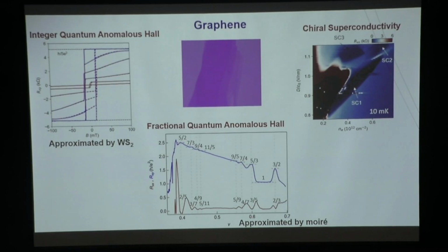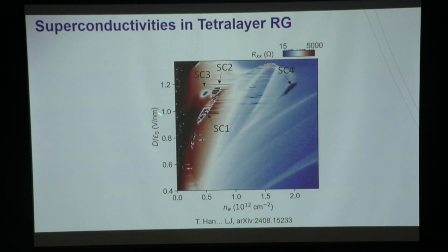Okay? In the last part, I'm going to show you something that, personally, I feel is even more interesting and in an even simpler setting. Without any proximity effect, without WS2, without spin-orbit coupling, without Moiré, just pure rhombohedral graphene, we got some very bizarre looking superconductivity that I will share with you. This time it's four-layer, it's not five-layer. Tetralayer rhombohedral graphene, and we do the same trick by applying charge density, gate displacement field, tuning the gate voltages, right? And we measure the longitudinal resistance RXX.